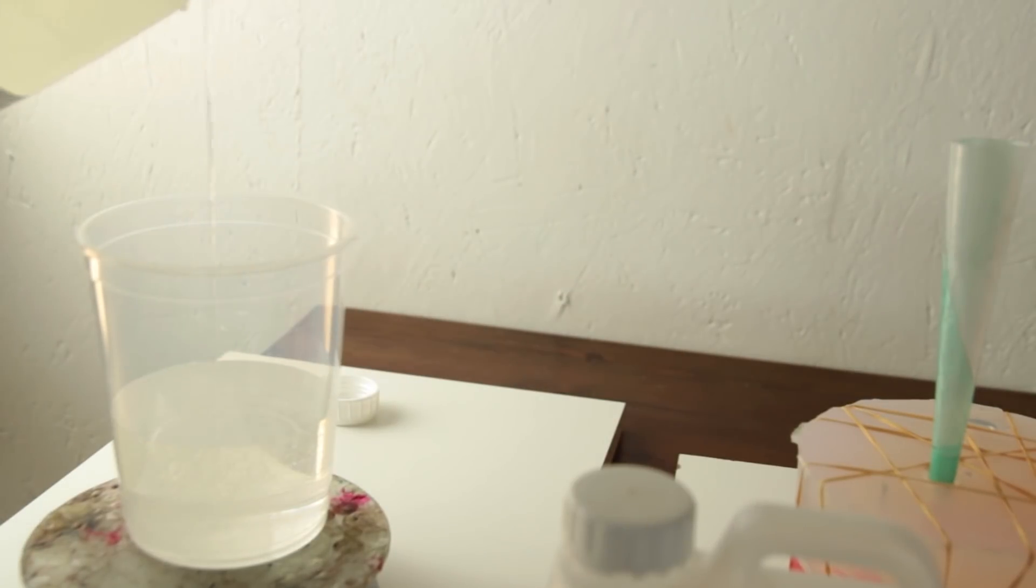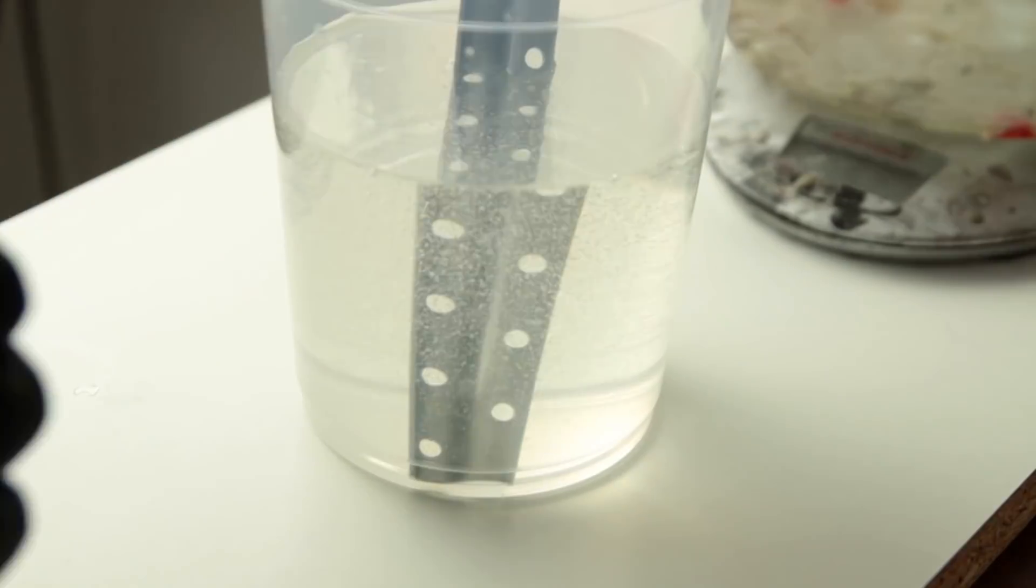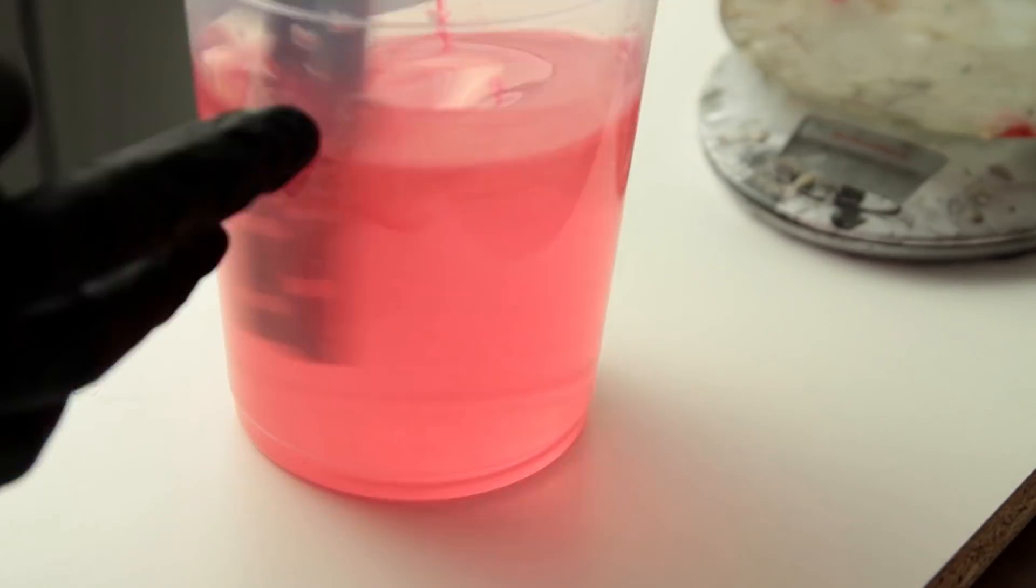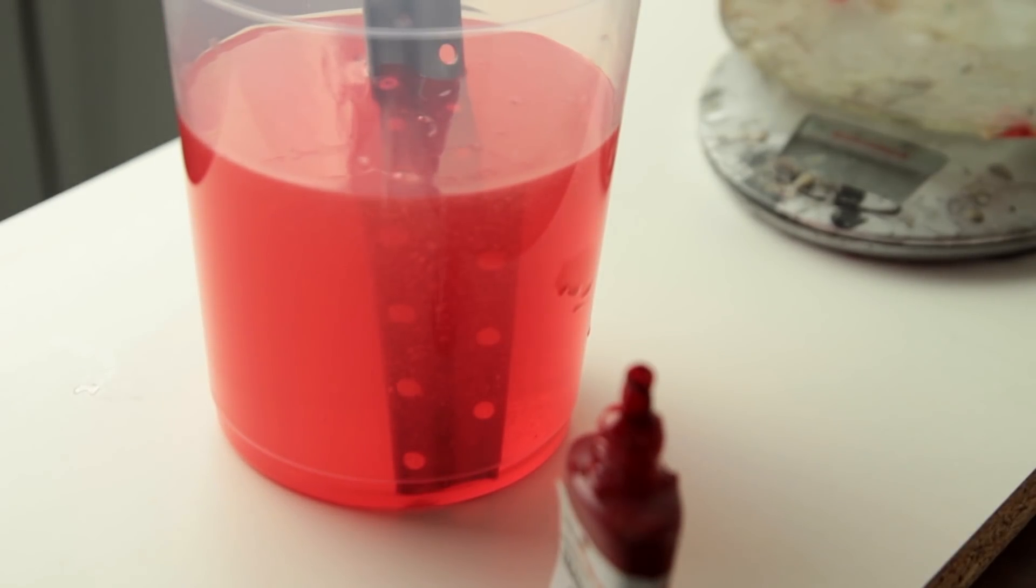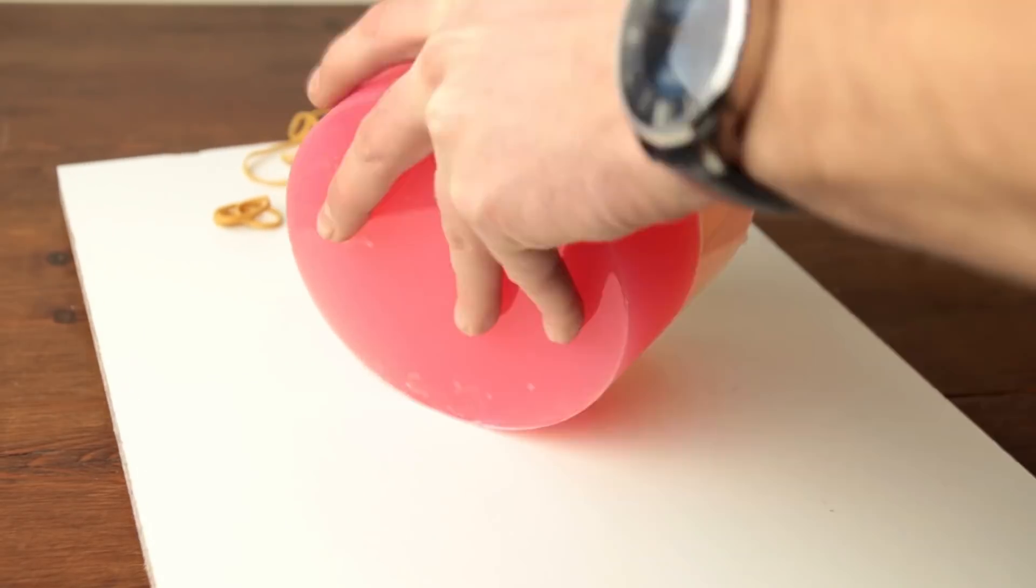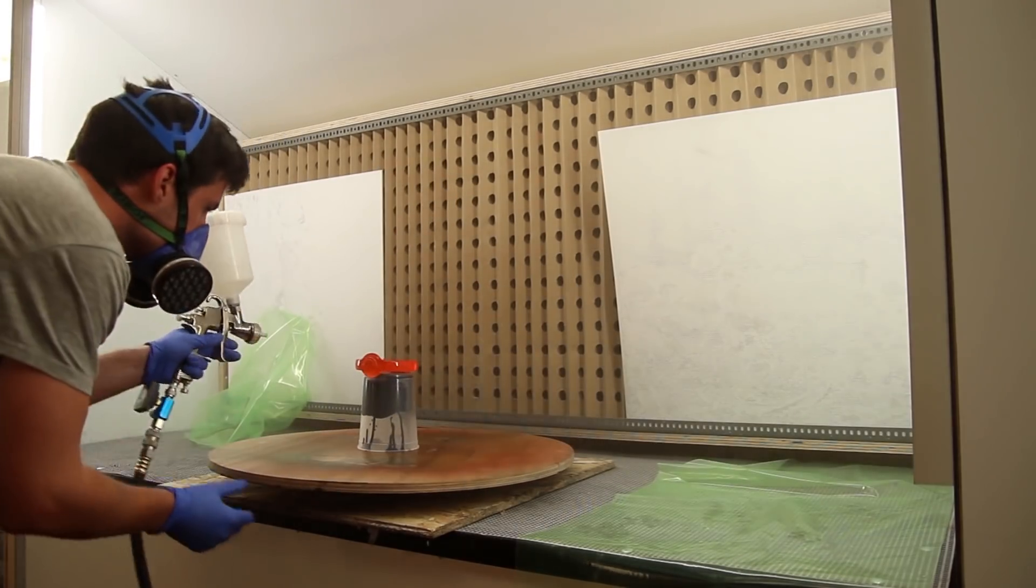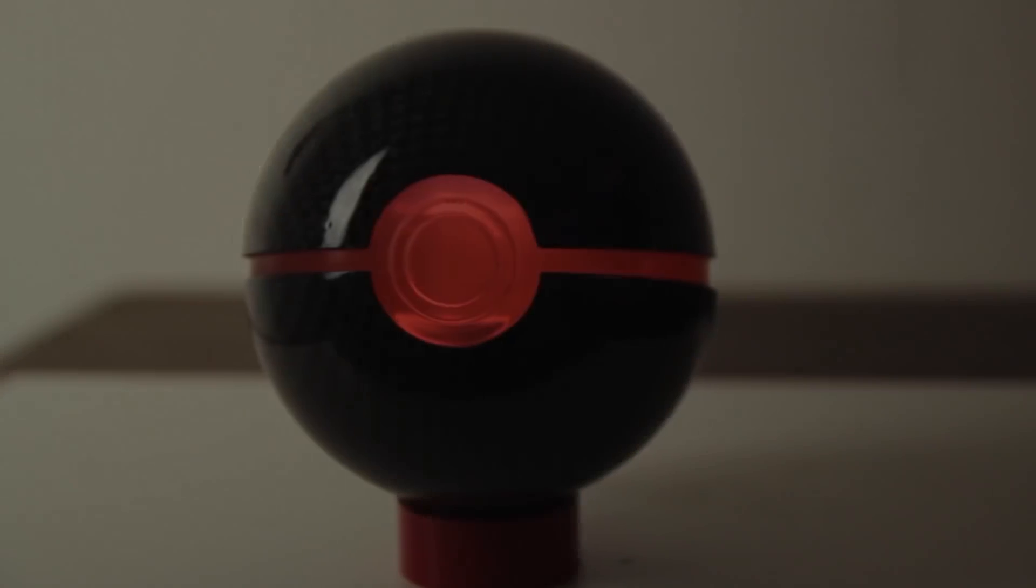I also did another project. I'll go into more detail in that other tutorial about making silicone molds, because I think it's a really cool thing. From a master you can make different finishes and multiple parts. It's like injection molding but with fast setting resins. Here is the look of the mold. The upper and bottom pieces are nicely matched together. Then we're ready to pour the resin. I'm using regular epoxy resin, the infusion resin with the slow hardener. Make sure you have a specific resin for this, because otherwise if you're pouring such thick parts there's a big chance your resin will overheat and crack in between.